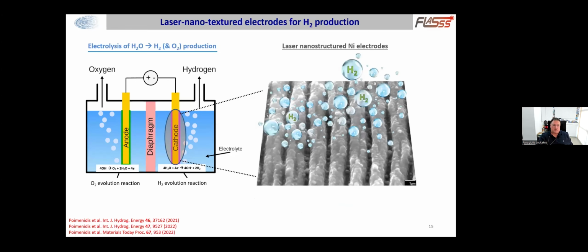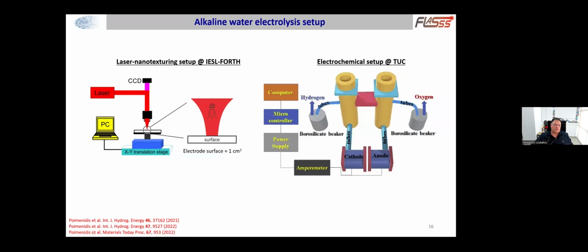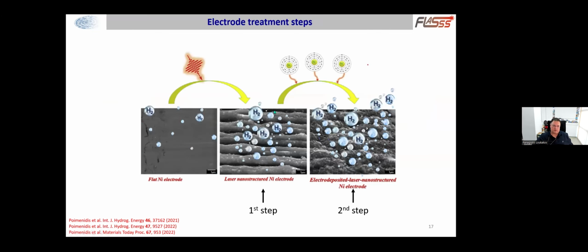Following this, as I said, closing this parenthesis and going back to our problem, which is the increase of the efficiency of these electrodes, we apply lasers on these electrodes in order to increase their surface by fabricating basically ripples and structures in these surfaces. We do this by employing these laser nanotexturing setups at FORTH, and our partners in the Technical University of Crete employ custom-made electrochemical setups in order to provide electrochemical analysis and characterization of the fabricated surfaces and actual measurements of the hydrogen produced by these samples.